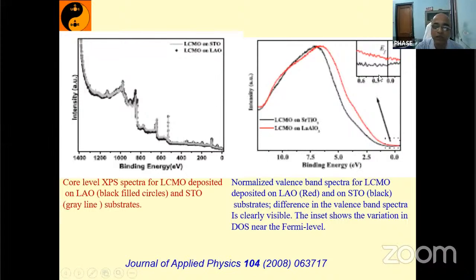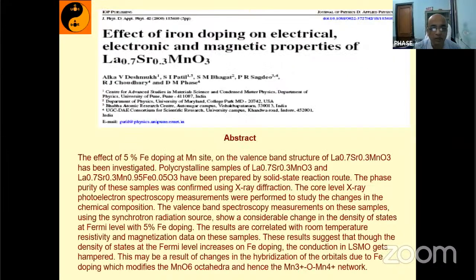And what is the difference? Basically, the density of states near the Fermi energy levels are different. And you know that if the density of states are different near the Fermi level, then the interaction of this material with other materials, if you use it as a sensor, will be different. So that is basically the fine details that can be found out using synchrotron-based photoemission spectroscopy. So these are some of the examples. I will not go into the details of all the other things.